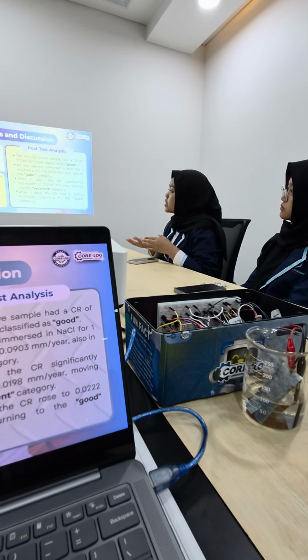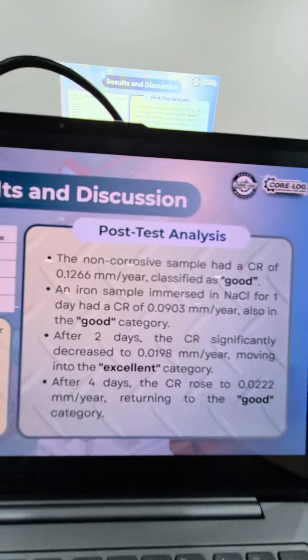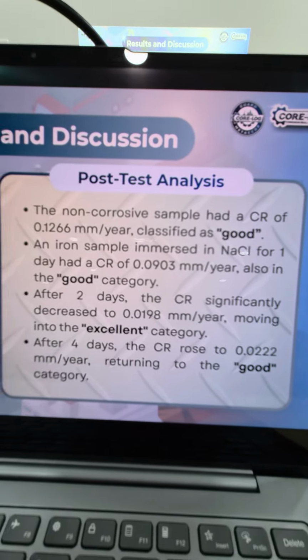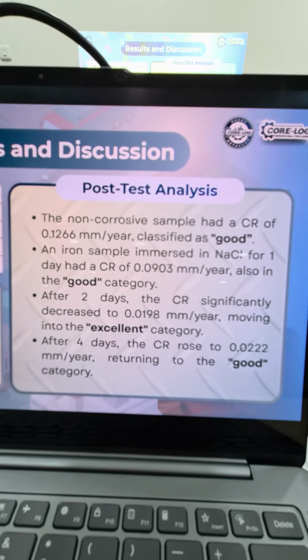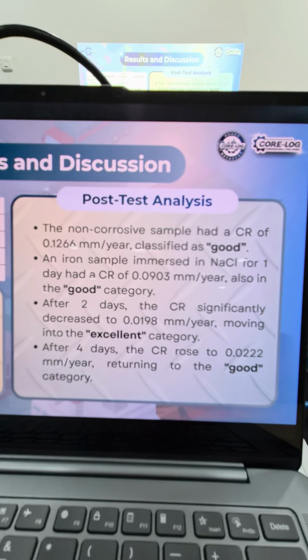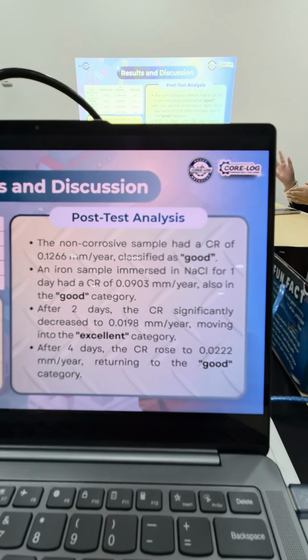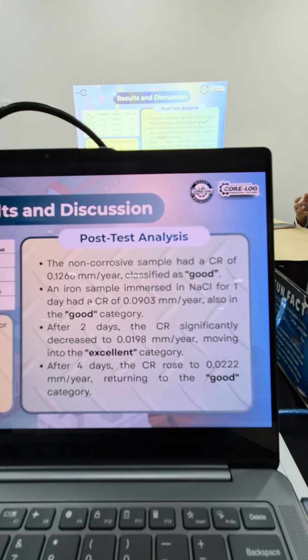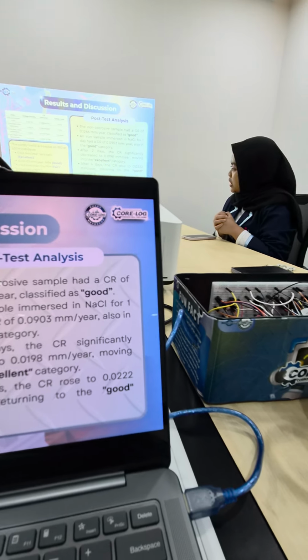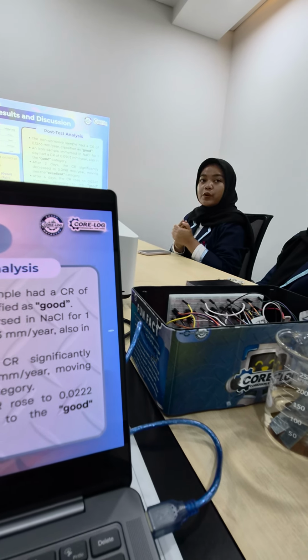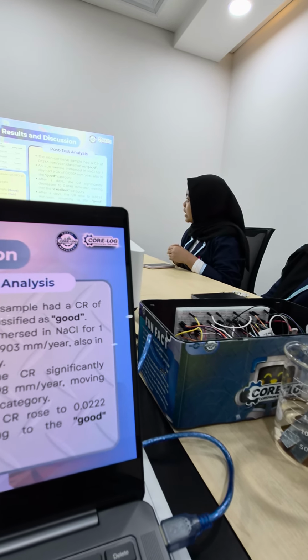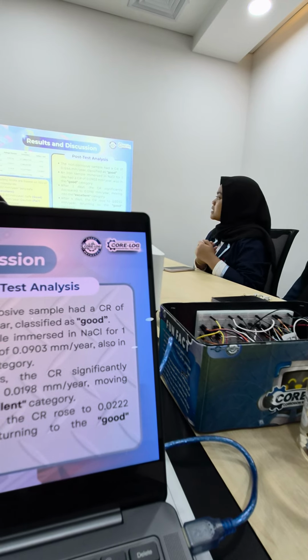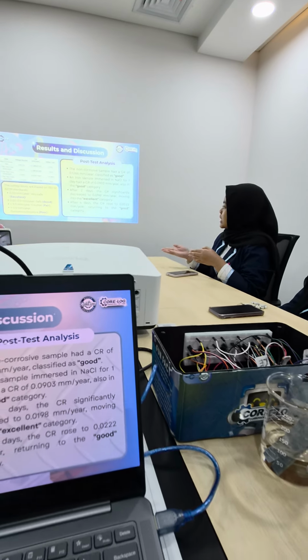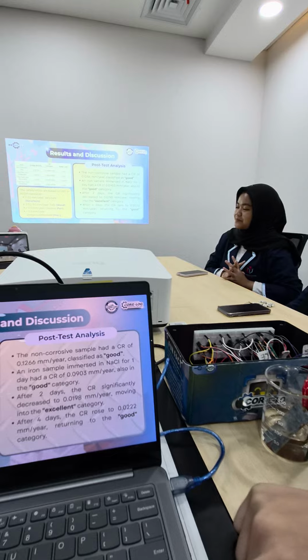And the third data, 2-day sodium chloride iron immersion, the corrosion rate is 0.0198. The safety limits based on ISO standards classify it as excellent. And for the last data, 4-day sodium chloride iron immersion, the corrosion rate is 0.0222, and if we see the safety limits based on ISO standard, it's classified as good.